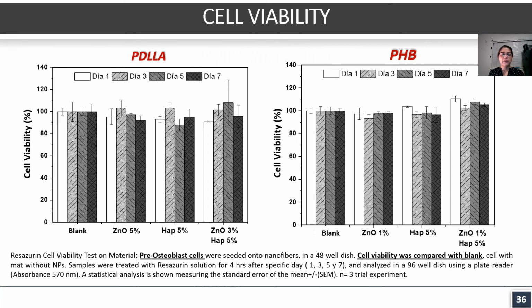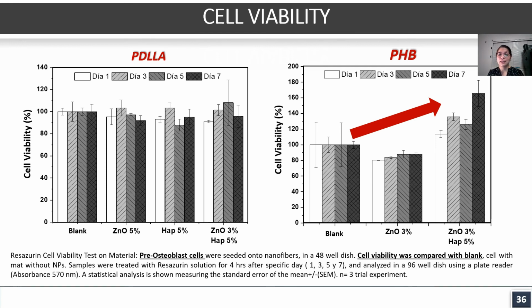For the study of the influence of nanoparticles on the cell behavior, a representation of cell viability was considered based on the blank. Regarding PDLLA, no significant changes in cell viability were observed, which means that the nanoparticles in this system are not exerting a cytotoxic effect on the cells. Regarding the PHB, it was evident that an increase in the concentration of zinc oxide in the ternary system promotes greater cell metabolic activity, despite the opposite behavior observed in the binary system at that concentration.